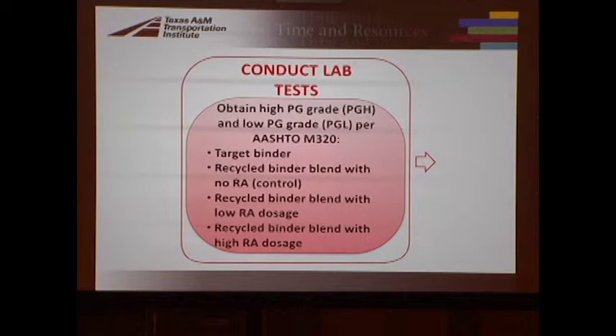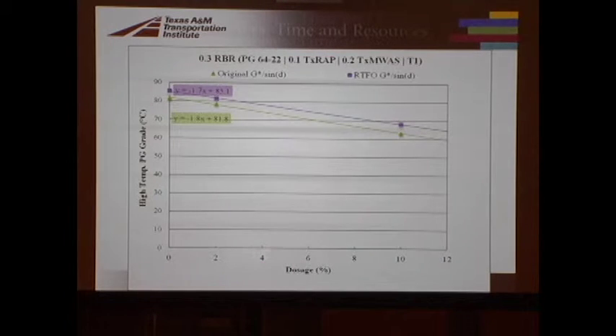Okay, then you got to grade it. So you get the PG high temperature grade or PGH and the PG low temperature grade just by AASHTO M320, just like we always do. We do that for the target binder. We do that for the control binder with no recycling agent, and then for the 2 ones with a low and high dosage. Okay, and then when you plot these, we basically plot the PG high temperature grade versus the dosage. We're going to have 3 points, 0%, 2%, and 10%.